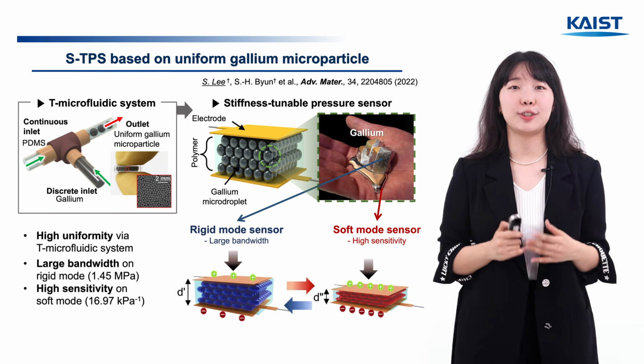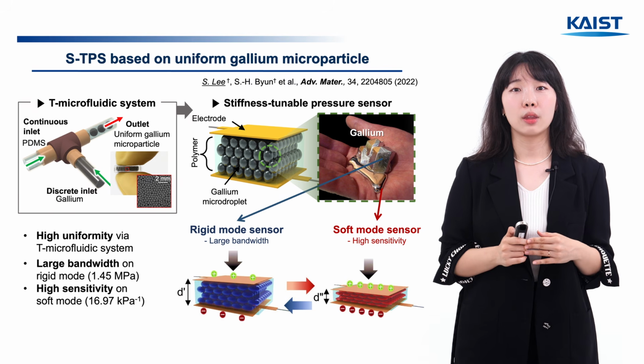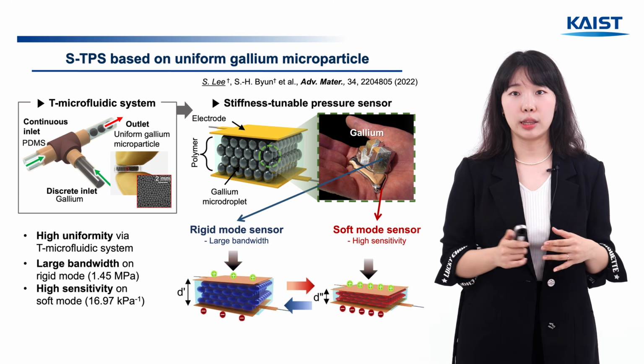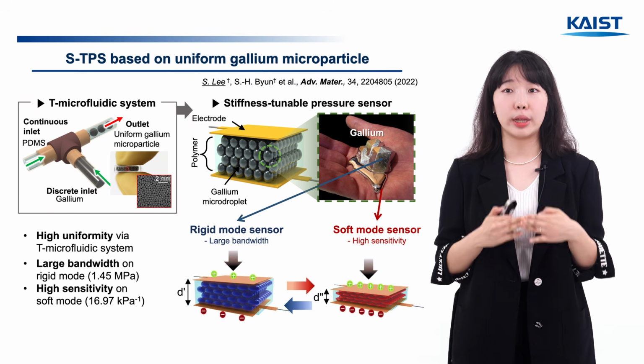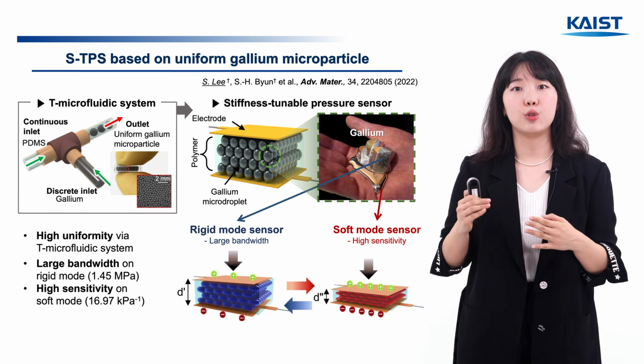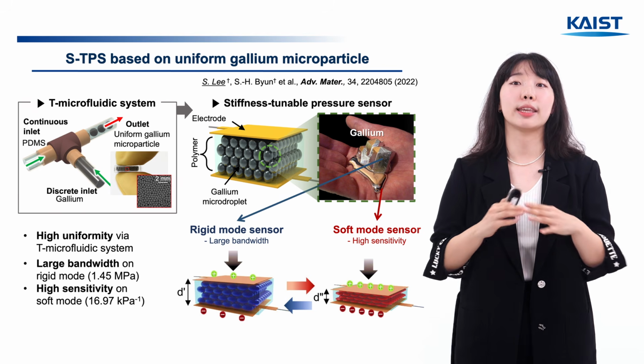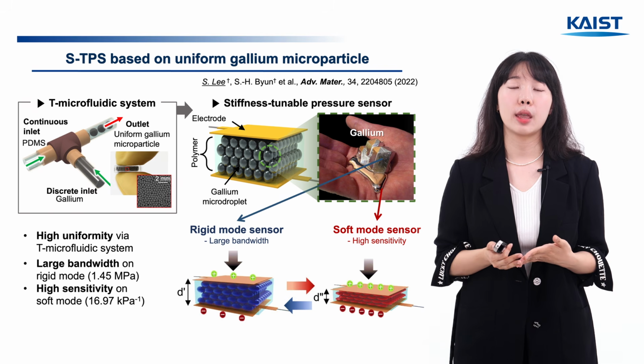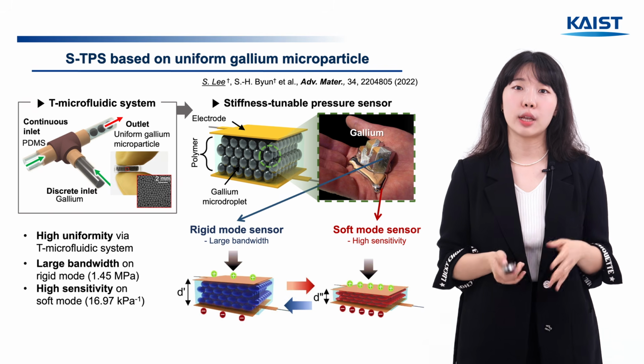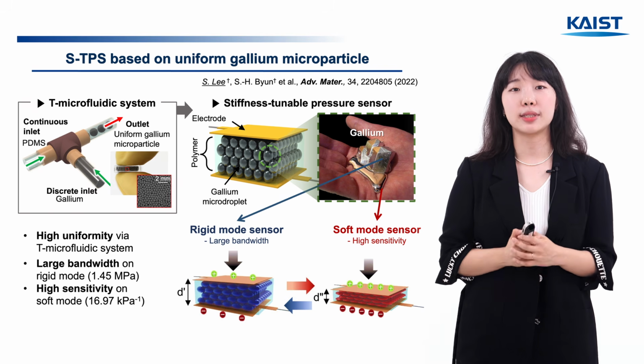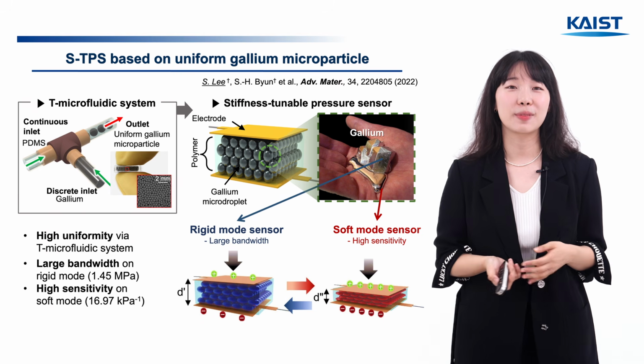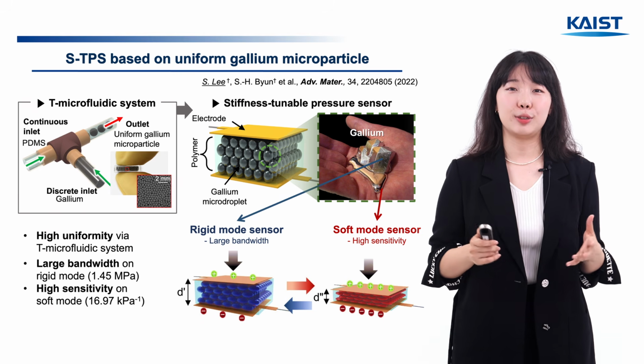Fabrication uses a T-shaped microfluidic channel. Uncured PDMS and liquid gallium go into the two inlets, and at the outlet, uniform gallium particles come out encapsulated in the polymer. Placed between the two electrodes, the LMPC becomes a capacitive sensor. The result is a high tuning ratio.